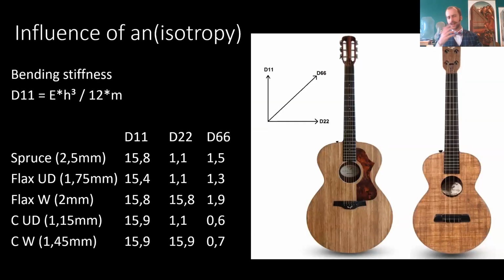So now, okay, I want to make music instruments from these fibers, but where do I start? You have a lot of variability. Some fibers are stiffer than others, so I need to make some calculations. First, you have, of course, the issue of the fiber orientation, so the anisotropy of a material. Here you see two instruments, a guitar and a ukulele, made by the same company. And in the guitar, they put all the fibers, these are flax fibers, in one direction, while in the ukulele, they put the flax fibers in two directions.